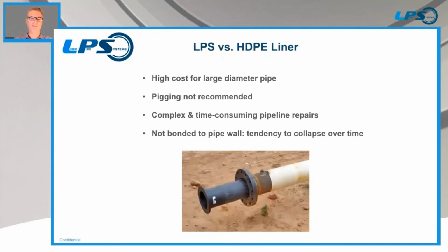There's definitely some limitations. First off, larger diameters, the cost really gets up there when you get to larger diameter pipe. The pigging is a big issue. Pigs are known to get stuck in the pipelines, and several engineers don't recommend pigging just because they stress the liner. The liner is not bonded to the pipe wall, so as the pig goes through it, it stresses the liner and can cause it to sag, and that's one of the major issues. That is that over time, HDPE liners are known to sag off the pipe walls. At least for concentrate lines in Chile, most engineers have told me it's not a question of if they'll collapse, it's when. And generally that time frame is in that 15, 20-year time frame.